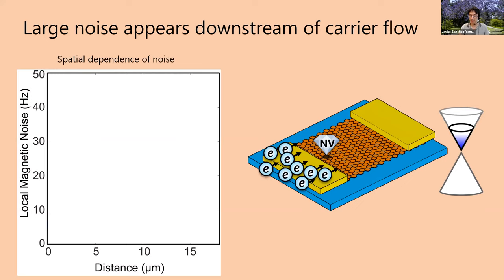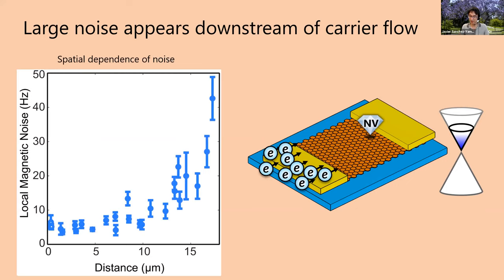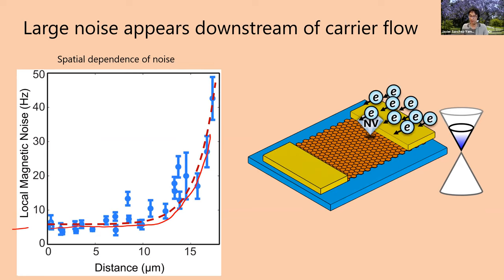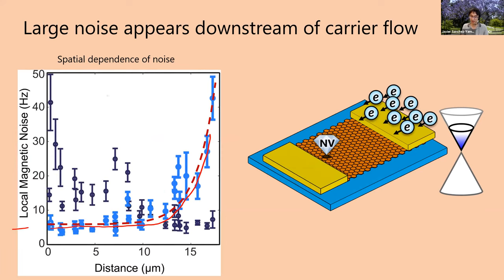And so just as the last thing, the last thing that we could do is map out the current noise at all these different points of our devices by measuring different NV centers. And what we saw was that indeed, the local magnetic noise grows exponentially as we go across the device in the direction of the carrier flow. And if we flip the direction of the current, the profile flips the other way around, growing in the opposite direction.